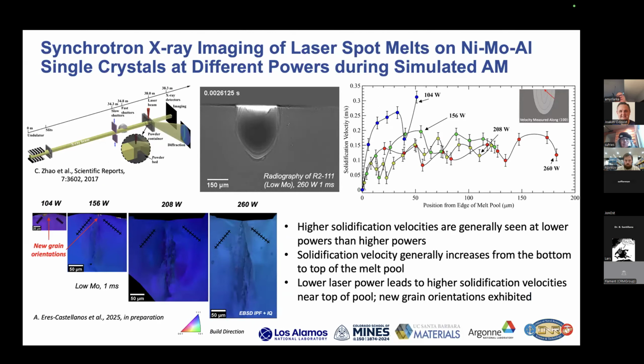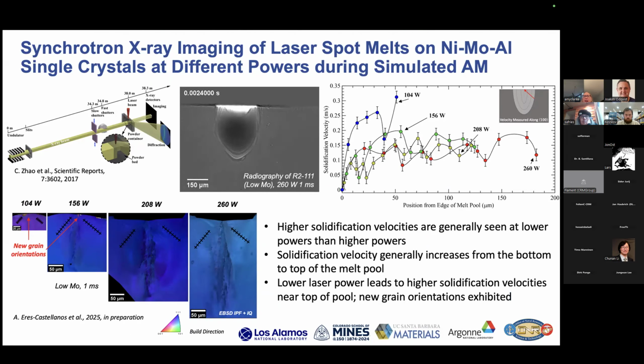So the extreme end of rapid solidification that we look at with DTEM, where we're really looking at velocities on the order of 1 to 2 meters per second. For additive manufacturing, we actually have to dial this back a bit. Usually we're looking at velocities of a meter per second or less, really tenths of a meter per second. And so this is some work that we've done trying to better understand additive manufacturing.